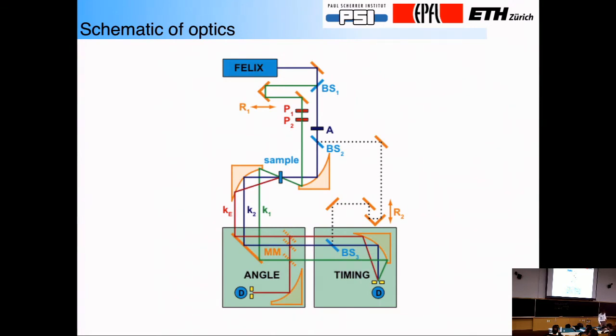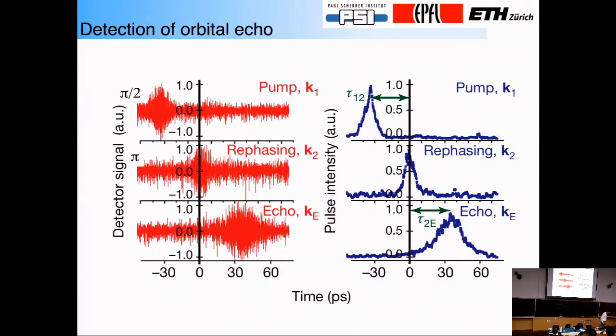This is the instrument. I won't take you through it since it's a theory center. But what's important here conceptually is that we're doing an experiment with 4 different beams of light, 3 of which are coherent copies of each other. I'm showing you a pump, and this is a pi/2 pulse. I have a rephasing pulse, which is a pi pulse, and then I have an echo, which comes out of the sample just by itself after these pulses have come and gone.